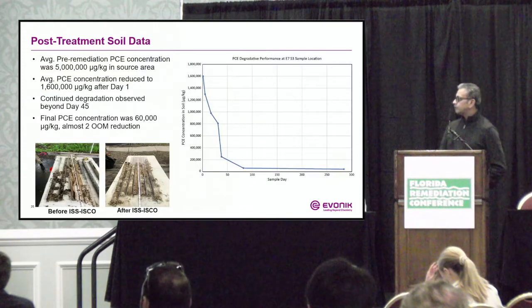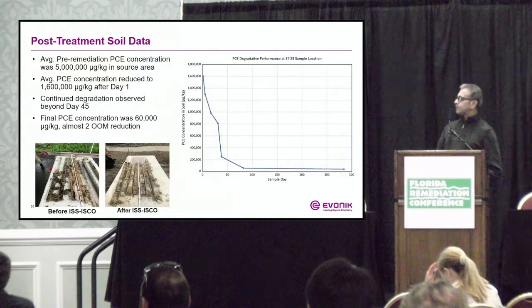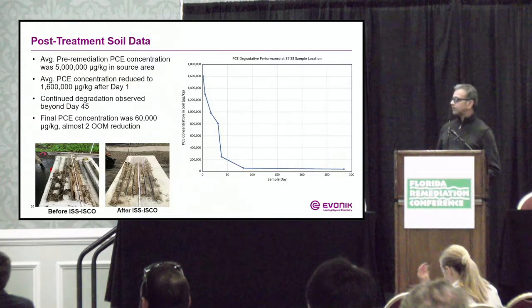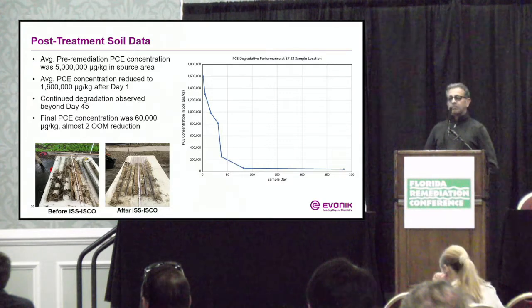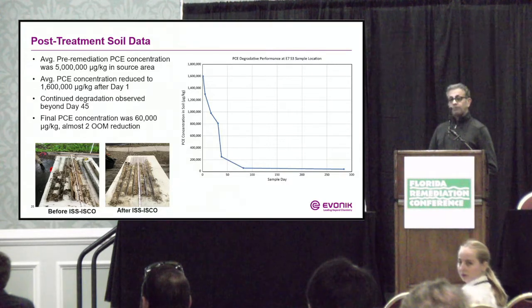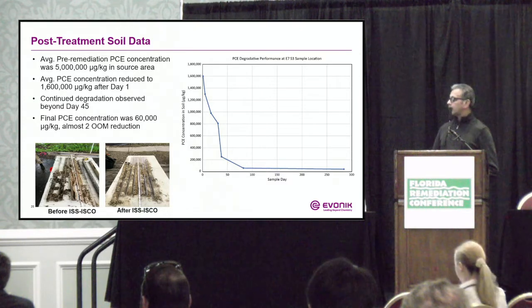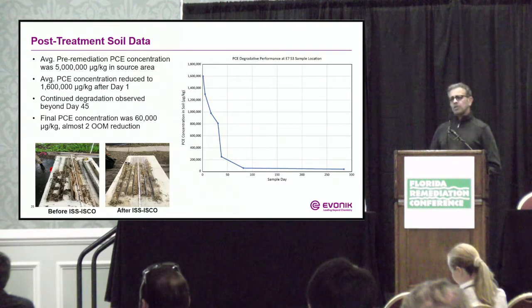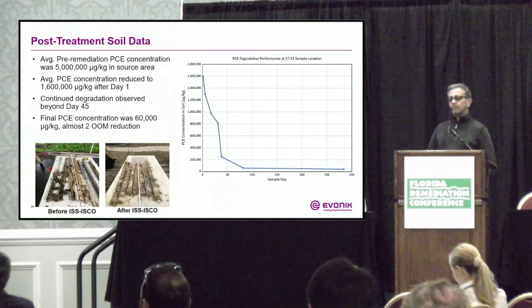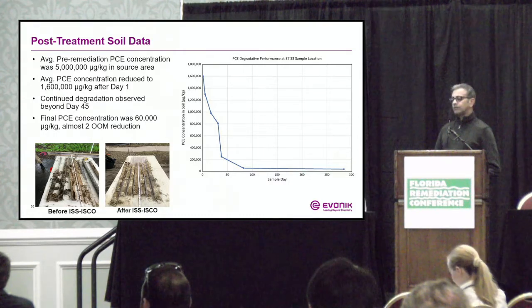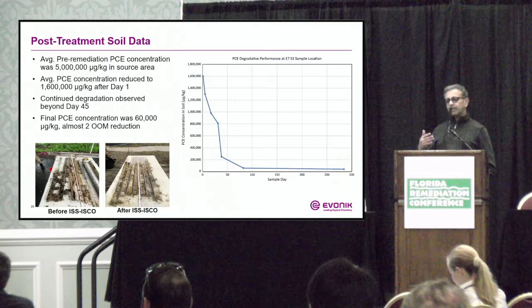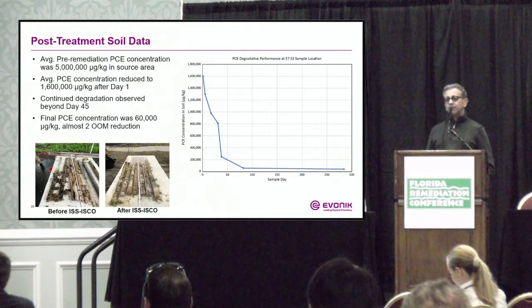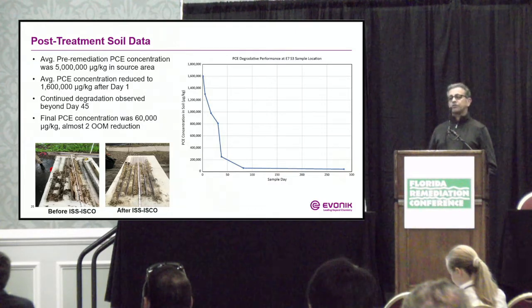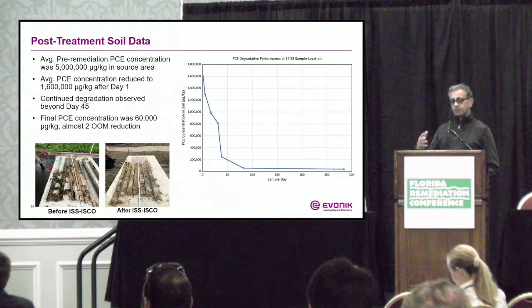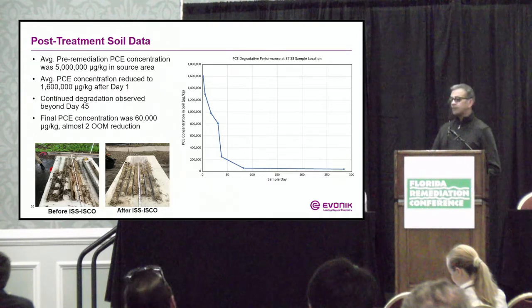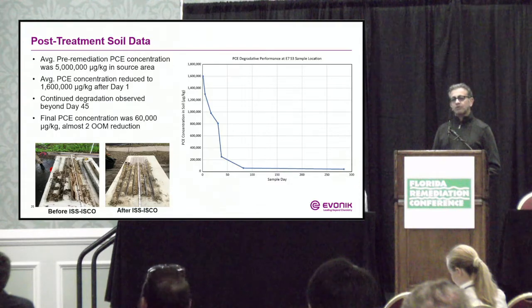So here's the data on the soil. The average PCE concentration in the source area was about 5 million micrograms per kilogram prior to the mixing. After the first day, the concentrations were down to 1,600,000 micrograms per kilogram. After the treatment, we were taking samples and monitoring. The destruction continued for about 45 days, even after the mixing was done. The final PCE concentration was about 60,000 micrograms per kilogram.